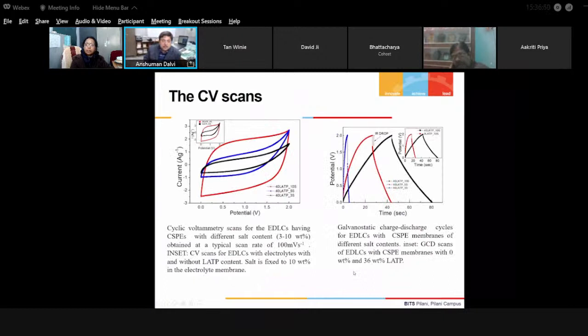The CV scans show hysteresis and featureless behavior up to a voltage of 2 volts, which we have taken, and we can see that when the salt is more, the box-like nature is more apparent. When the Nasicon content is more, the box-like behavior is also more apparent, and that means the electrical transport is more in the polymer matrix, which leads to a better value of the supercapacitance.